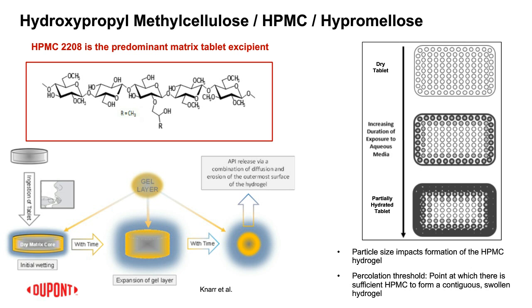This is called the percolation threshold, right, for a number of folks who are familiar with that term. Percolation threshold is impacted by really two factors, or other things, right, but two primary factors. There's the particle size aspect, and there's the concentration aspect. So with a finer particle size, you can get away with a little bit lower concentration of HPMC in your formulation. The coarser the particle size, you might need a little bit higher concentration of HPMC in your formulation to be able to achieve this percolating network of particles throughout the matrix tablet.